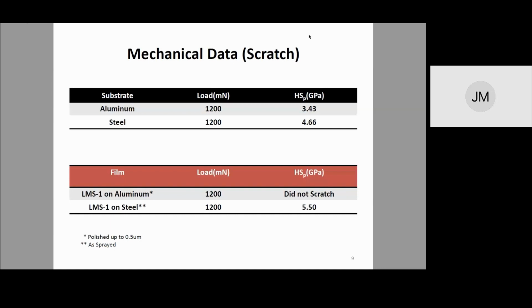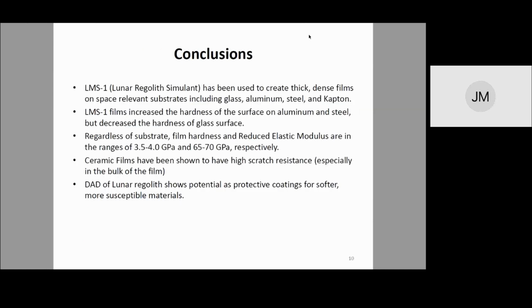The LMS1 film on steel, however, was tested as sprayed, and so we did get a scratch out of that as the surface was rougher and more susceptible to abrasive damage. The scratch hardness on the film for the steel sample was still about a gigapascal harder than the substrate itself. Next slide, please.